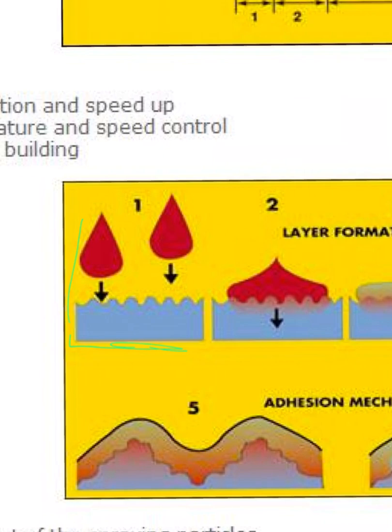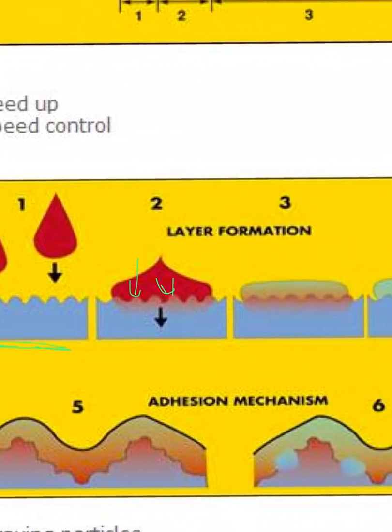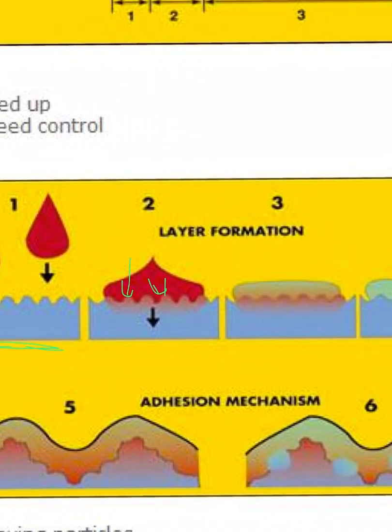And the hydroxyapatite hits that surface, and when it does so, it's hitting a relatively cold, maybe even room temperature surface, and so it sees cooling rates of like 1,000,000 degrees a second or some crazy number like that. And so what can happen as that process has occurred is you can get some amorphous calcium phosphate.